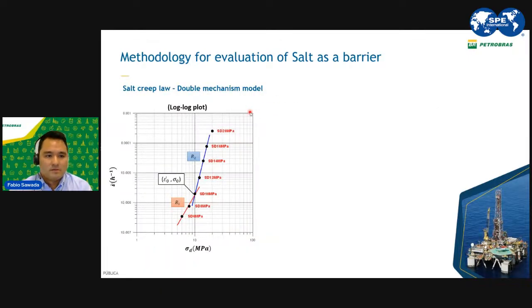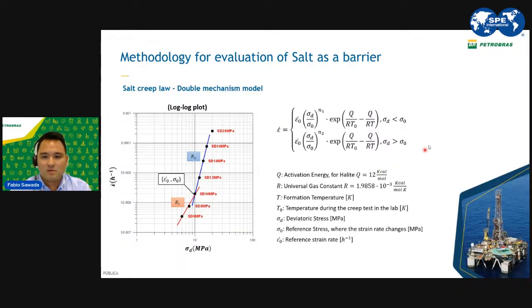To model the behavior of salt, we use the double mechanism model. It is known as double mechanism because, as you can see here in the chart, it has two different behaviors. We have two different inclinations here. So we have a reference deviatoric stress that in this case would be 10 MPa. When we reach this deviatoric stress, the behavior of the salt changes. So the creep rate increases. This is why the law is called the double mechanism model, and this would be the equation that represents the creep rate of the salt.